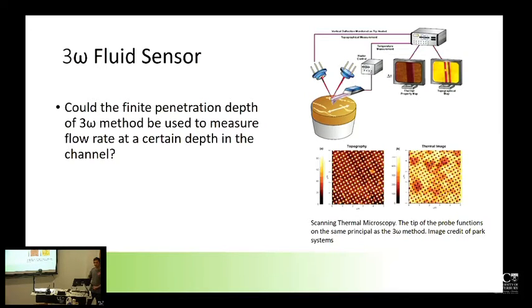So the foundation idea is not so uncommon in solid systems. This is what's called scanning thermal microscopy. The idea of this is you have an AC, like a 3 omega thermometer, like I've just been talking about, except embedded into the tip of an AFM. So this can scan or raster across the surface and measure thermal transport away from the tip, and you can build up a thermal conductivity profile or a heat transport profile over a whole range of places. So this is a topography of, I think, silicon nitride pillars on some silicon, and then they can take a corresponding thermal image of it and measure that the thermal conductivity of the silicon beneath the pillars was much higher than that of the silicon nitride on the surface.